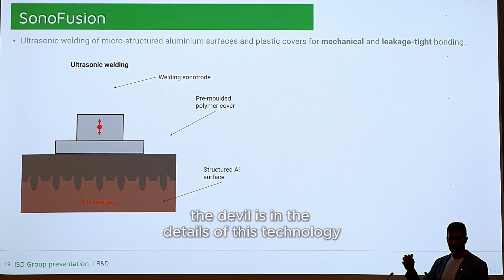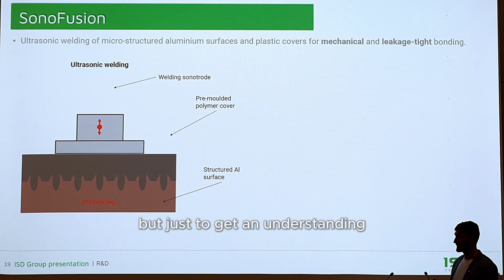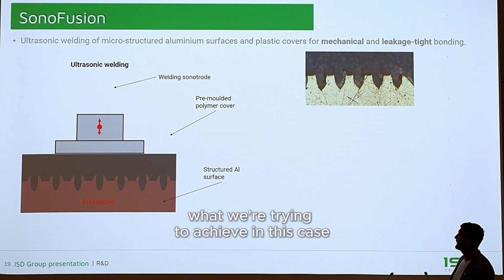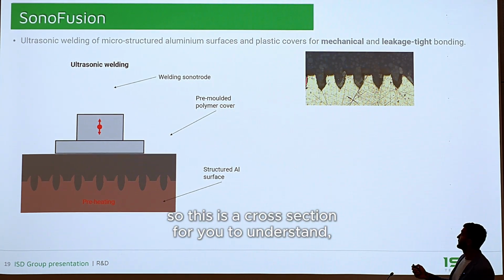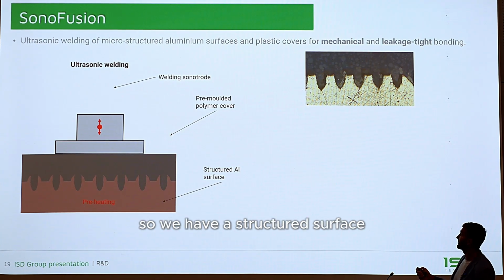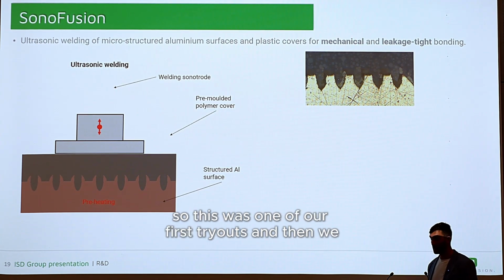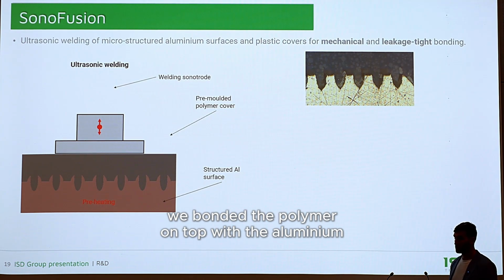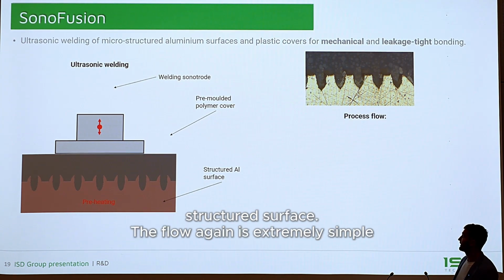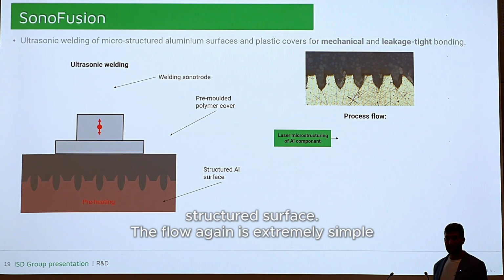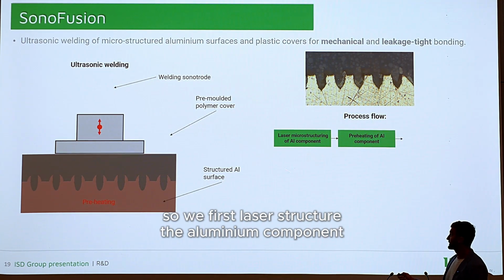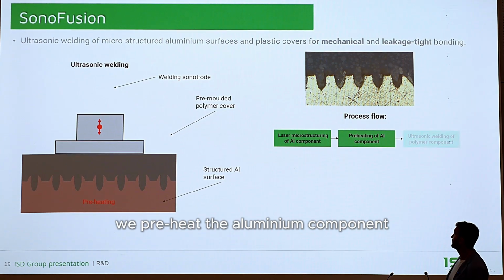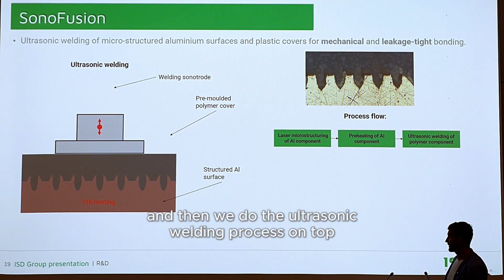Obviously the devil is in the details of this technology, but just to get an understanding of what we're trying to achieve in this case, this is a cross-section for you to understand. So we have a structured surface. This was one of our first tryouts, and then we bonded the polymer on top with the aluminum structured surface. The flow, again, is extremely simple. We first laser structure the aluminum component, we preheat the aluminum component, and then we do the ultrasonic welding process on top.